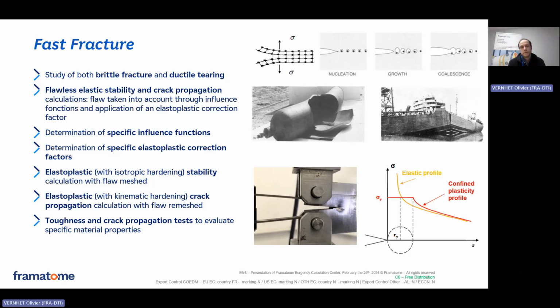And if it's not enough, we might develop some specific influence functions specific to the geometry that we want to study. We might also develop some specific elastoplastic correction factors because, as I said, we begin with elastic calculations, so we use elastoplastic correction factors, but sometimes the ones that are codified are too pessimistic, so we want to optimize them. So we might perform, specific to the geometry we study, elastoplastic correction factors. If it's not enough, then we might perform some elastoplastic stability calculations.